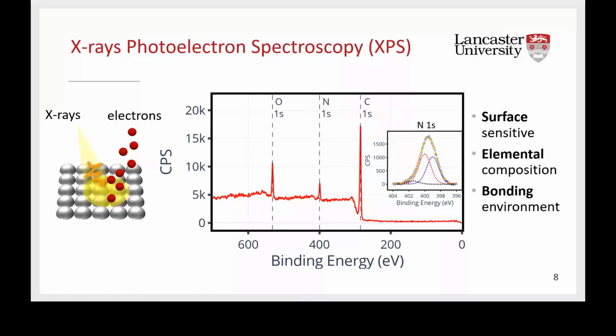What you get is this kind of spectrum you can see here, with the binding energy and the number of counts, and some peaks appear in the spectrum. Then we can assign each peak to an element in the material. For example, you can see carbon, nitrogen, and then oxygen.